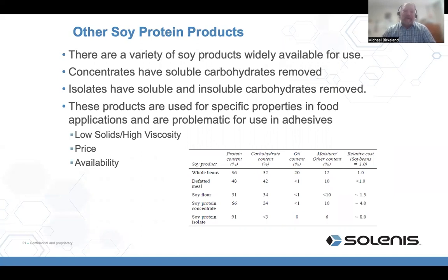The biggest problem really is the low solids, high viscosity issue. Part of manufacturing wood products is the removal of water, a hot press. And when you have so much water to remove, it's really hard to get the strength you need while removing the water that you have to get rid of so that your panels don't warp afterwards. So as high solids as possible is ideal. And that's something that these kinds of products definitely struggle with.